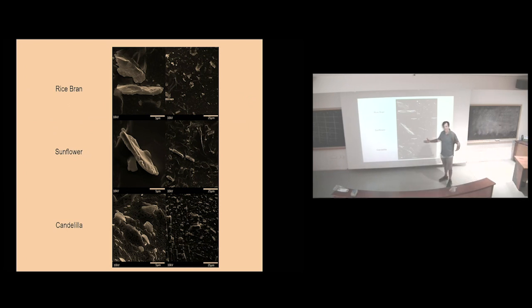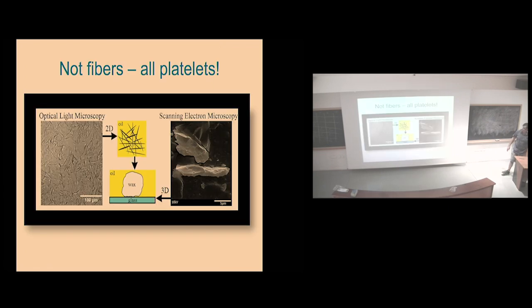Like, needles, what? Waxes, if you look at all the literature in waxes, they form platelets, right? So why don't we go to the SEM and do some etching with an organic solvent and let's see what we get. And we found that a whole bunch of these platelets were just sitting up like this. They weren't needles. They were like platelets standing on their side. And that was what's giving us some of the morphology that we associated. And we put out there that even though you think that you have needles, if you call these needles from a micrograph, in reality this is what we got from the SEM. We actually got platelets that were in there. But they were on their side, FYI.